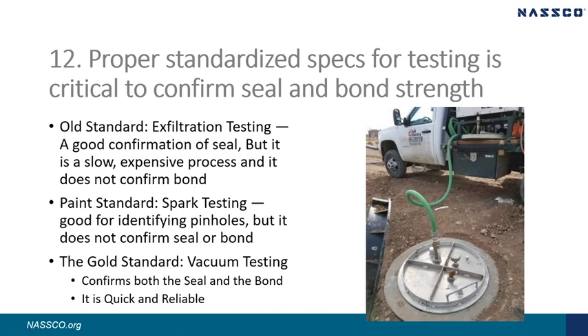The gold standard for acceptance testing for a rehabilitated manhole is vacuum testing. It confirms seal and can provide a qualitative sense of bond strength. We recommend vacuum testing to the ASTM C1244 standard.